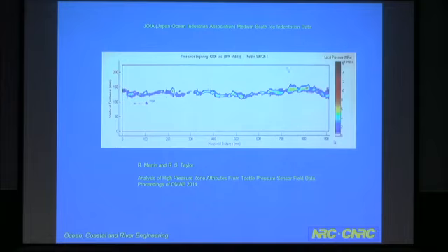And same thing for the JOIA tests that were conducted in Japan, edge-on type tests, and you get a hard zone that develops through the mid thickness of the ice, and crushed ice is above and below that.